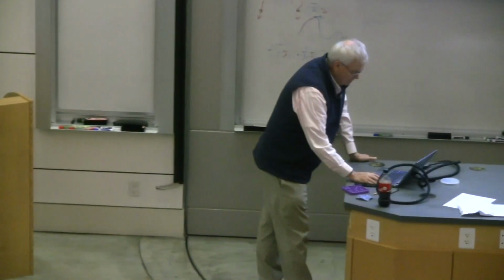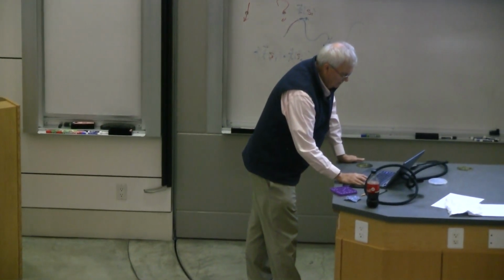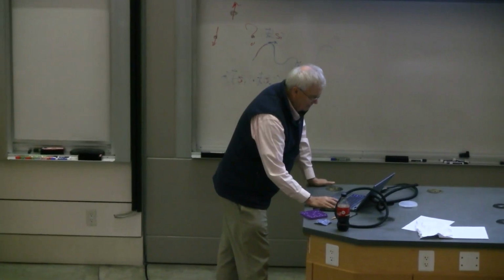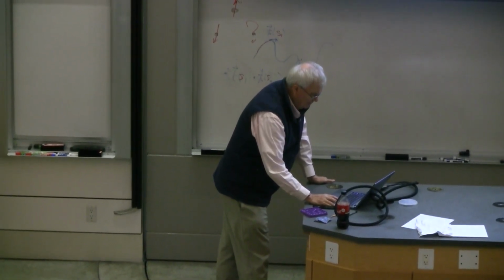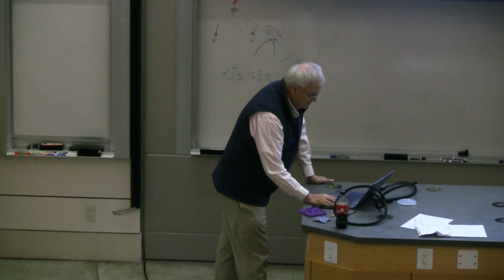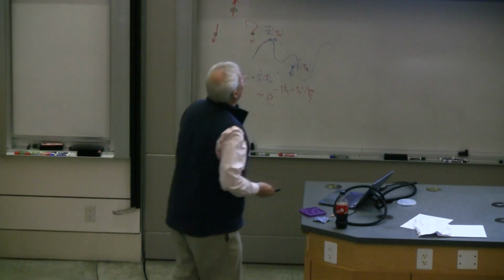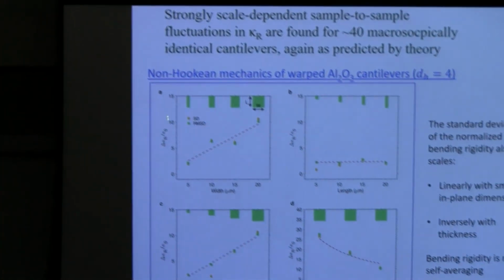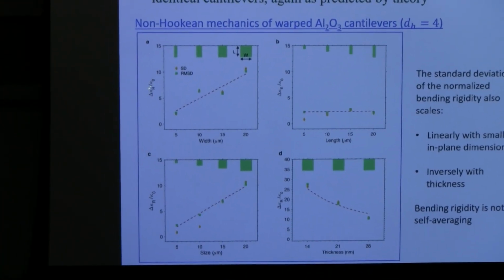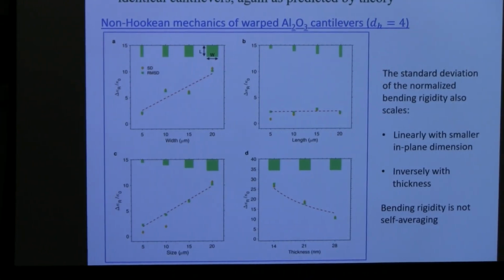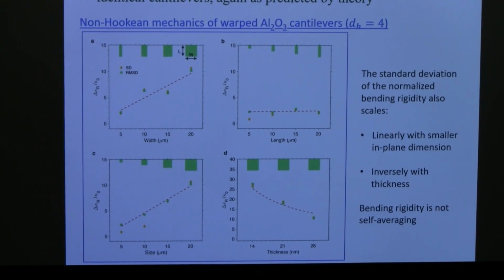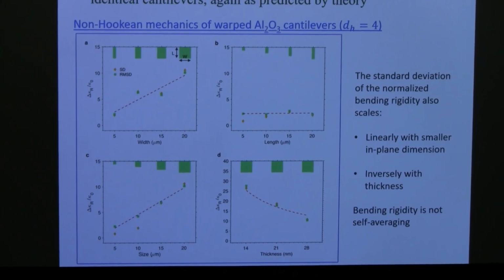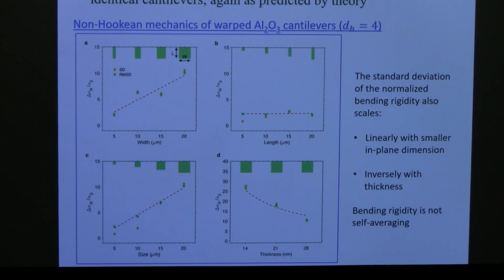And I might even have evidence for that if I back up enough here. Let's take a quick look. So I go back before I did this kind of stuff, and even further back. And here, the strong scale-dependent sample-to-sample fluctuations. So this is the standard deviation of the bending rigidity from its background value, 25 times larger, and it grows linearly with system size. So the death of self-averaging, as well as the death of Hooke's law. Too bad, but it's worth knowing about if you're trying to make a device.